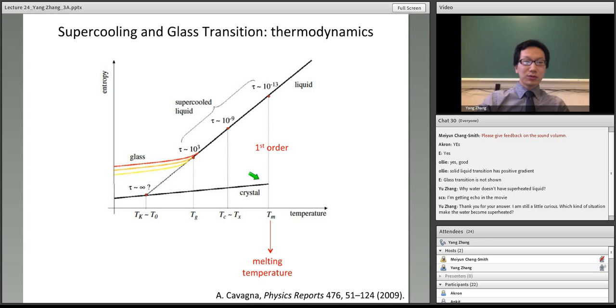Now, if we cool down the liquid carefully enough, and we have mentioned that cooling down carefully enough is actually more complicated than just saying. How do you cool carefully enough? There are a lot of phenomena going on. Trying to avoid this first-order phase transition really depends on the nucleation rate or the crystallization rate of the material, and its comparison with its relaxation time. But that is obviously beyond the scope of this talk. So let's just say we can avoid this first-order liquid to solid phase transition, and we can go into this metastable supercooled liquid regime. Okay, and if we keep doing that, eventually we'll hit the so-called glass transition temperature.